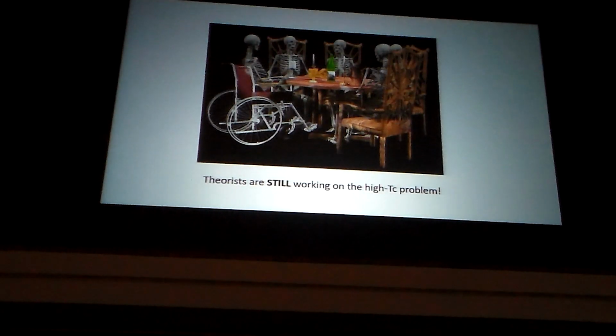So it is possible for Coulomb interactions to cause this attraction. If this is correct, then the superconductivity in the high TC cuprates is caused by this superexchange interaction. So it's a magnetic interaction. Now, how many people actually believe this? Not in this audience. If I went to a conference of so-called cuprate experts, how many would believe this? Well, 50-50, my guess. So the bottom line is still out. However, there are still people working on this problem.